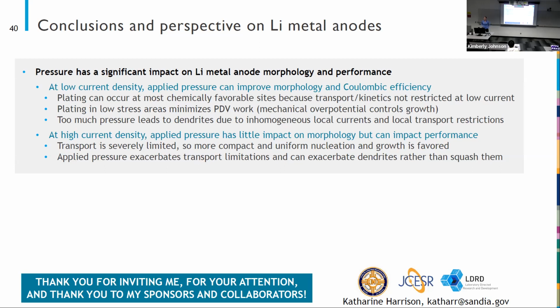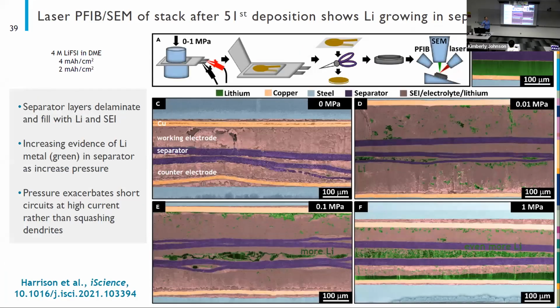We've also tried to do this with pouch cells. So everything I showed you was a coin cell, and I kind of cheated a little bit and didn't explain this top portion, but we have to use coin cells with this particular process. And we were using pouch cells with these pressure studies, right? So what we did is we opened up the pouch cells and, using ceramic scissors, would cut a coin cell sized hole in our pouch cell. And then we would put those in a coin cell as a way to protect them to get to the SEM. And then we'd freeze it all in the SEM.